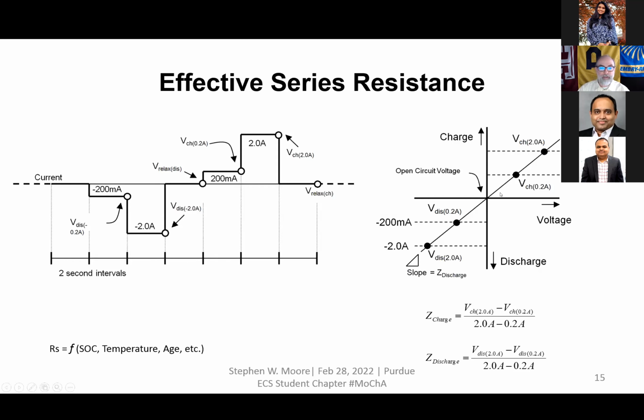And the slope of this line is Ohm's law, which is a function of voltage and current. And then I can draw out the R sub S of this cell by observing the voltage drop at different currents and then drawing a line and finding the slope. And I can pretty well characterize this R sub S. Now, I'll have to perform this at different temperatures, because the R sub S changes with temperature. When a battery's cold, it sags more, so that means the resistance is higher. When the battery is warm, the resistance is lower, etc.